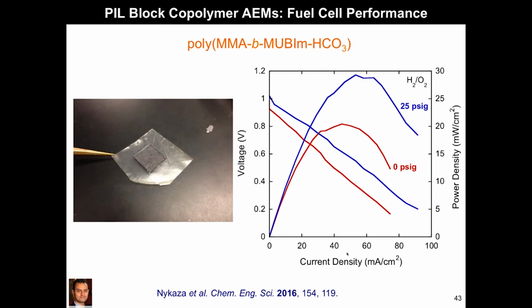And from this study, we basically learned that it works, which is great. However, the fuel cell performance could be improved pretty significantly. And probably the one thing that caught our attention was the lifetime was not great. So some of the in situ, ex situ chemical stability still, I think, needs to be worked out in this entire field. But I think the imidazolium, the specific chemistry we were looking at, was probably not chemically stable enough for the actual fuel cell application.